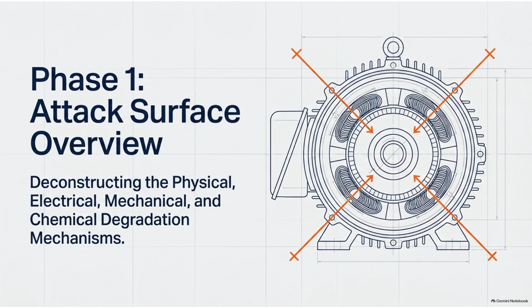A spark. Basically. According to Paschen's law, at certain small gap distances, the electrical field is strong enough to rip electrons right off the air molecules, turning the air into a conductive plasma. Wait, plasma? Inside the motor. Tiny plasma arcs, yeah. And this tiny electrical arc releases extreme localized heat and ozone. The ozone is highly reactive and literally oxidizes and burns right through whatever is left of that thermally degraded enamel layer we just talked about. That is insane. So the heat bakes the insulation until it's brittle, and the high-speed silicon carbide switches create plasma arcs that burn holes right through it.